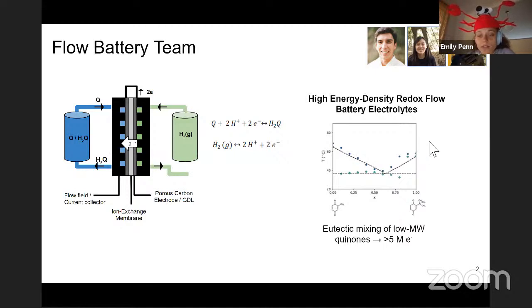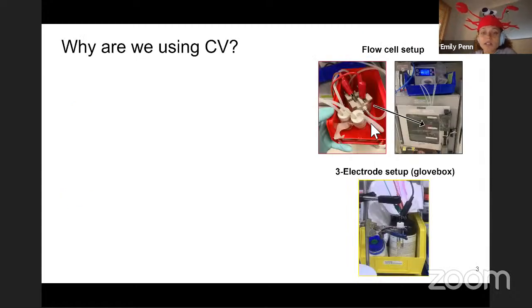So they found that when you mix different low molecular weight quinones, we can depress the melting point and make mixtures of these quinones that are liquid at lower temperatures. So ideally, this would allow us to mix together low molecular weight quinones to form a high energy dense quinone liquid, which you could use as a liquid electrode for redox flow batteries. So we're ultimately trying to build a battery.